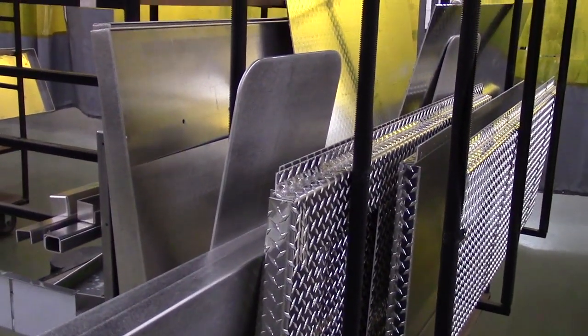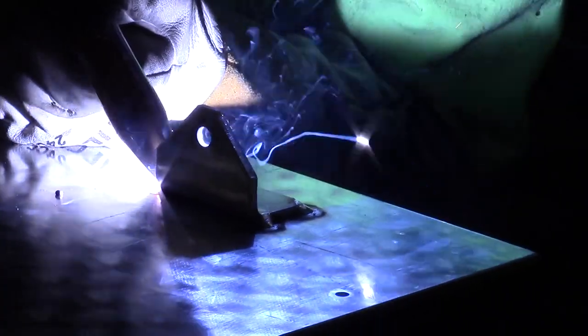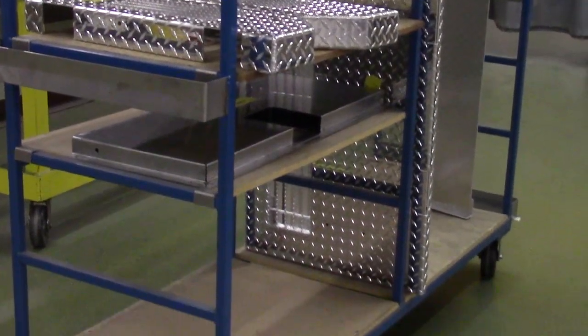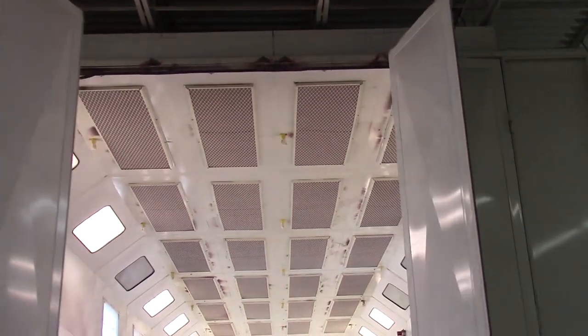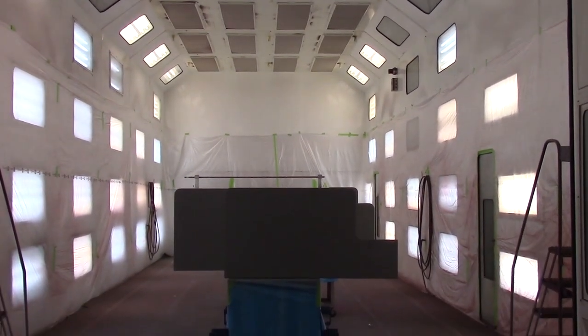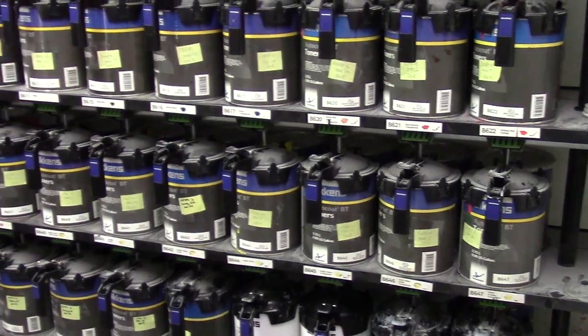Aluminum shelves, trays, steps, running boards, and dividers are all TIG welded to produce an aesthetically pleasing weld. Our manufactured in-house 304L stainless steel doors are also prepared in this area before going to paint. Fabricated parts are placed on carts sorted by truck number and assembly line cell. Stainless steel bodies are sent to the paint shop before going onto the assembly line. Our paint booth is large enough to fit a completed aerial unit — it is a downdraft paint booth and we mostly spray base coat/clear coat or two base coats followed by three clear coats. The painted components are then baked to 160°F for 60 minutes. We have the same paint system as our facilities in Ocala, Florida, to ensure that the cab and body paint matches.